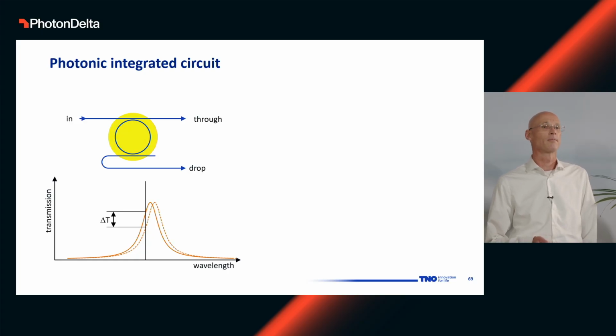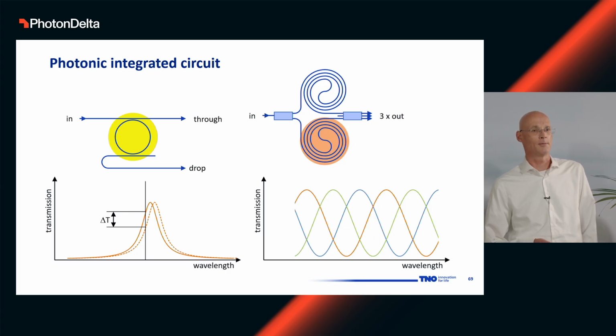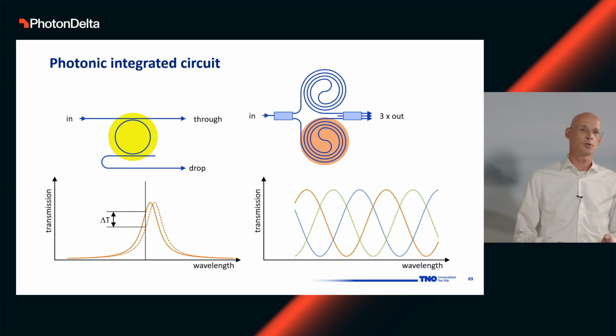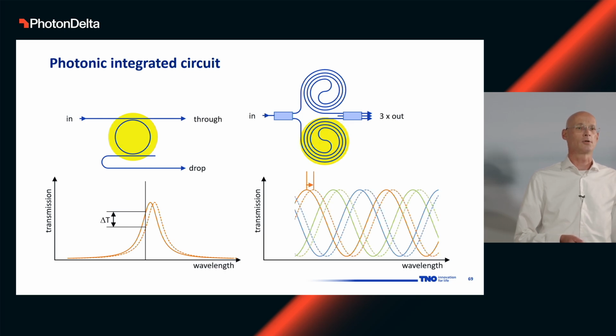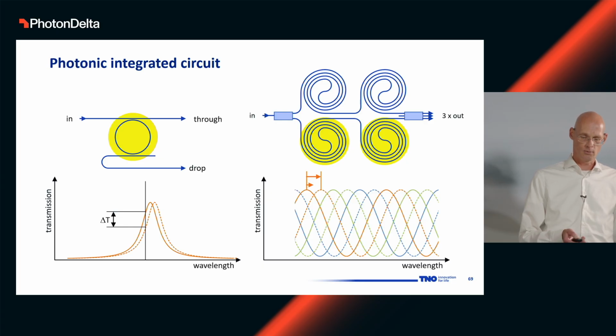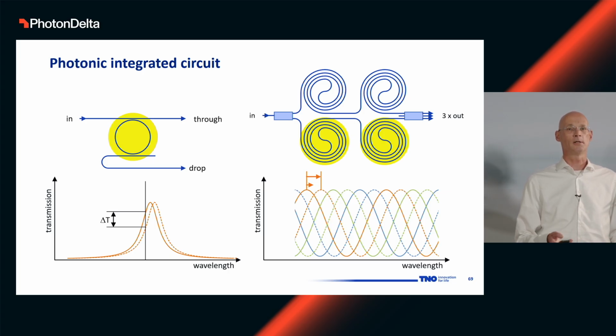The resonance will shift, and you measure a change in transmission. You can also do this with an interferometer. We like interferometers with 3 outputs. I'll come to that in the next slide. And then, of course, upon a pressure signal, you can see the interferometer signal also shift. It's a little bit more difficult to detect. So what you can do is boost the performance by including more membranes in the same interferometer. Here I have 2, so I boost the sensitivity by 2, but you can also take 10 or 20. This is where things become really interesting, because you can enhance the sensitivity quite a bit.